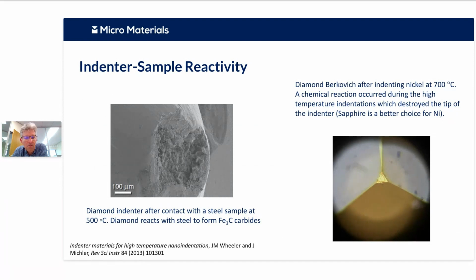Similarly, on the right, you can see a diamond Berkovich indenter in high vacuum. Nevertheless, it's been indenting nickel, and in this case, there's a flat end on the side. So that's not the indenter of choice that should be used for nickel. We use typically sapphire for testing nickel-based superalloys at high temperatures, and those are fine.